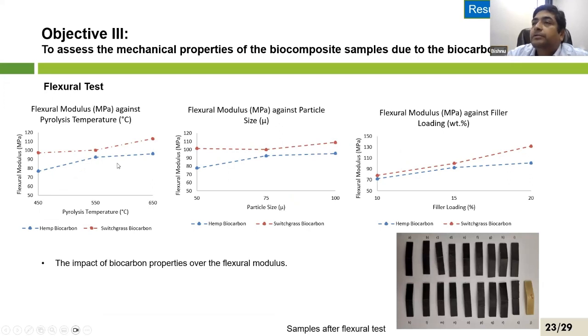Again, the flexural modulus gets higher at 650 because it gets very brittle when we take the 650 and use that. Similarly, at 100, it gets very brittle. So, 10, 15, 20. The 20 gives a higher flexural modulus. Very good.